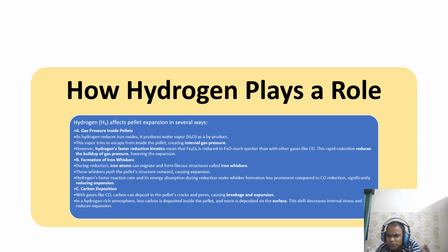So, hydrogen superpowers. Hydrogen is the MVP here. First, it reduces iron oxide super fast, creating water vapor that escapes quickly, lowering gas pressure. Second, it keeps those pesky iron whiskers in check, reducing expansion. And third, it shifts carbon deposition to the surface, preventing cracks. Hydrogen is the ultimate pellet protector.